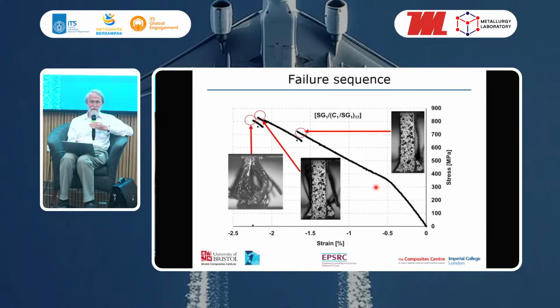But if you look at what happens, for example, with the single ply case, then we have fragmentation occurring here. That gives us the change in slope, quite a significant change in slope because we've only got 1 thin carbon ply to every glass ply. But then it goes quite a lot further before we get delamination. First on one side, you can see that surface ply has delaminated. Then at a higher strain, the other side goes, and we get this one delaminating here. And then at even higher strain, the whole thing fails catastrophically. So that's what happens in a direct compression.